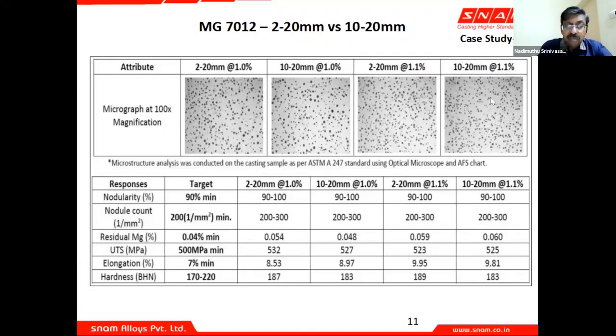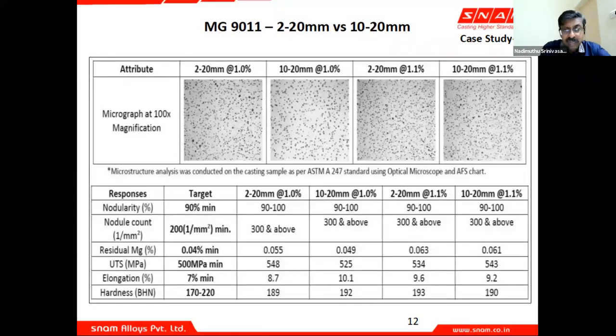Okay, so on a 7012 grade, again the experiments were conducted, and the same 2 to 20 at 1% and 1.1, 10 to 20 at 1 and 1.1. And here again you can find similar results. Another grade, 9011, where you have a magnesium of 8 to 10%, 0.8 to 1.2% of rare earth, and 0.8 to 1.2% of calcium. Here again, you will find the repeatability, the consistency, that a 2 to 20 is performing equally good as a 10 to 20 mm size distribution of the ferrosilicon magnesium at 1.1%.